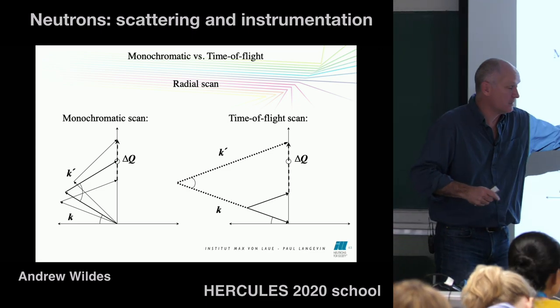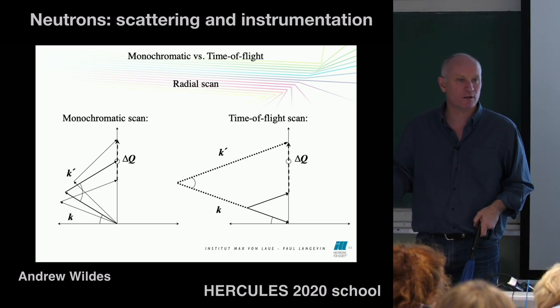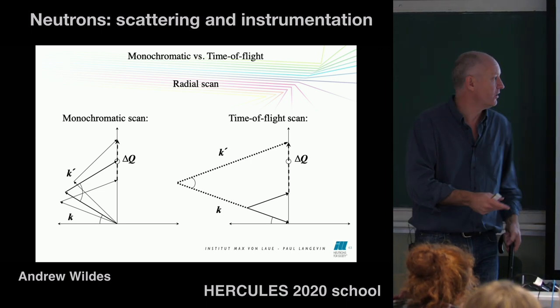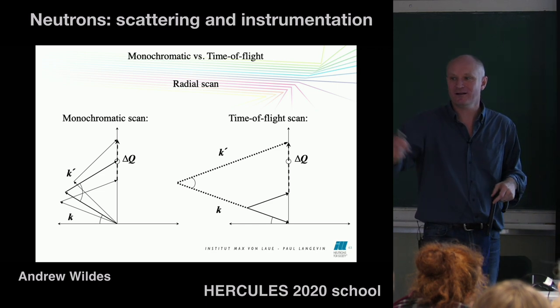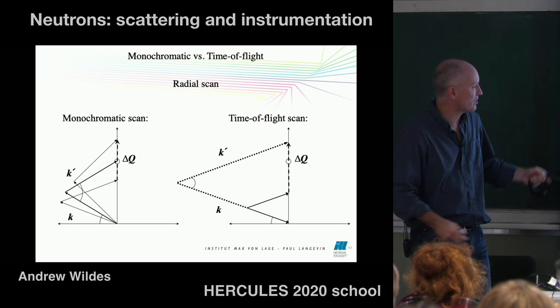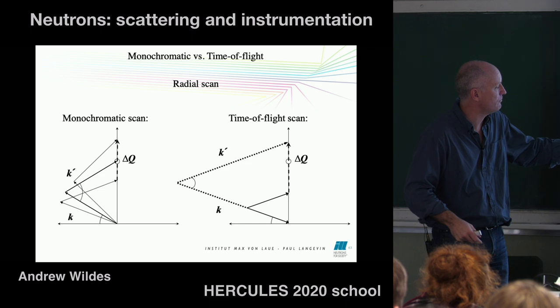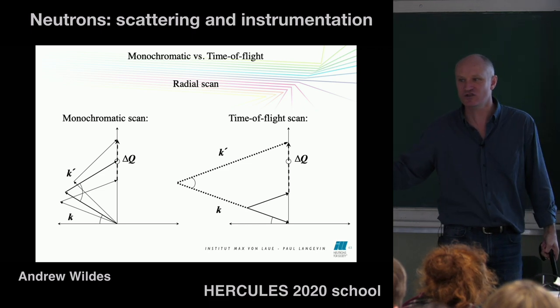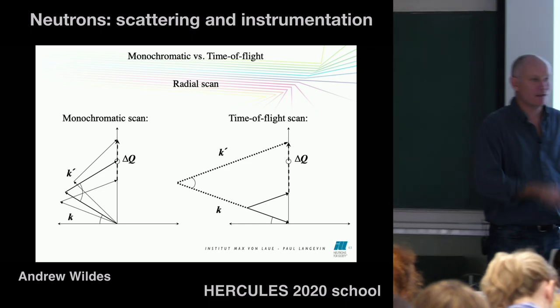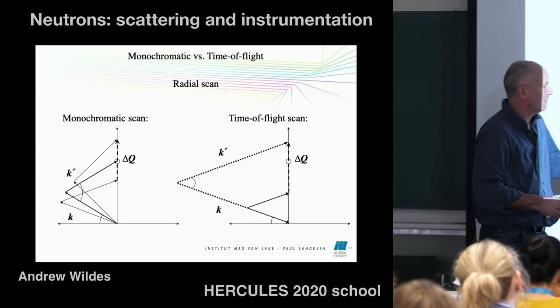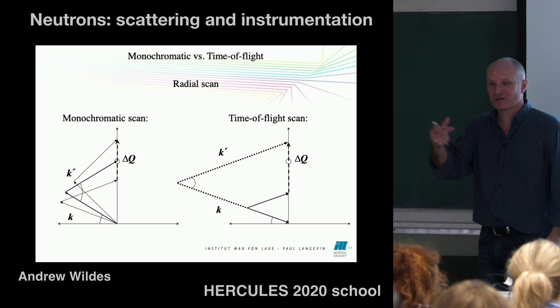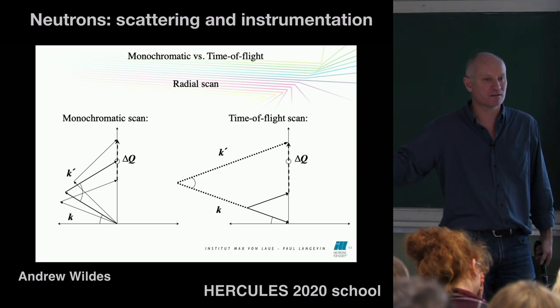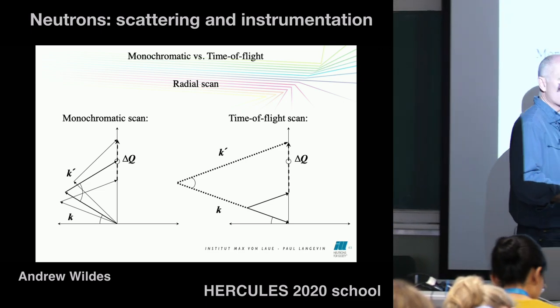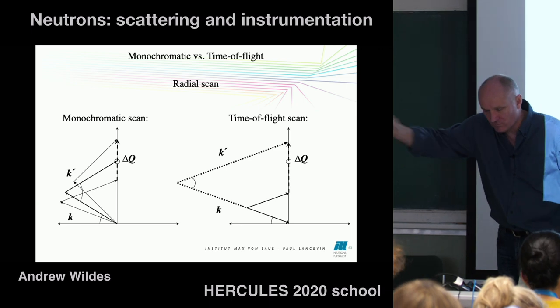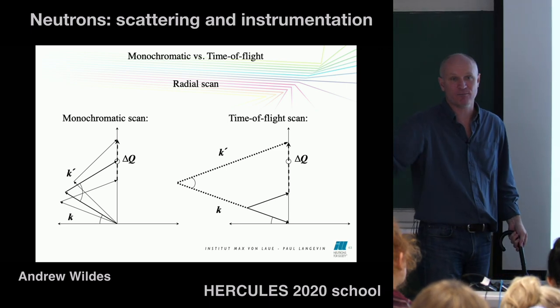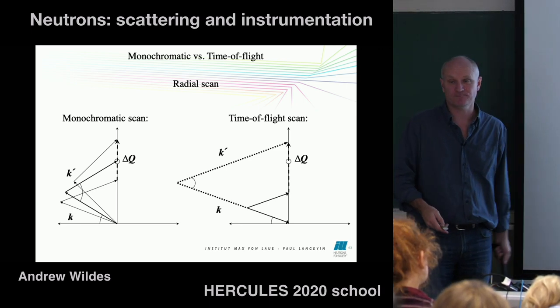That can make this technique very powerful if, for example, your sample changes with time. You want to know how this d-spacing might change. It takes you a certain amount of time to measure. Here, you're measuring point by point. So by the time you get from there to there, your sample might have changed, and you would never know. But here, if you measure for 5 seconds, what you've got is the average structure of your sample over those 5 seconds. And then you could do something like spectroscopic measurements where you would bin in time and you could work out how your sample changed with time. So there's an advantage here.